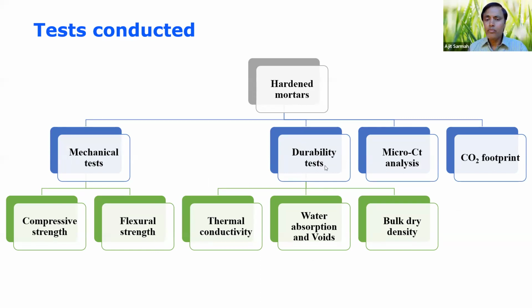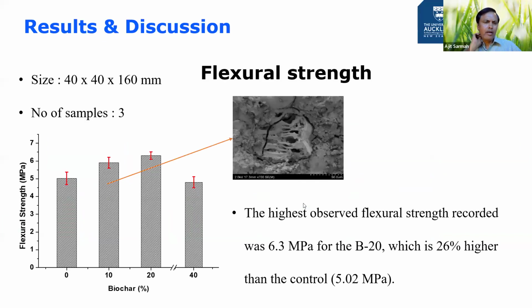We looked at the durability. We did some microcomputer tomography analysis, looked at the carbon dioxide footprint, looked at the water absorption, looked at the density of the mortars, and also we looked at the thermal conductivity. So I'll give you some findings, what we actually got. Cube size were very small, 40 millimeter, 40 millimeter, 160 millimeter. So we had 3 samples.